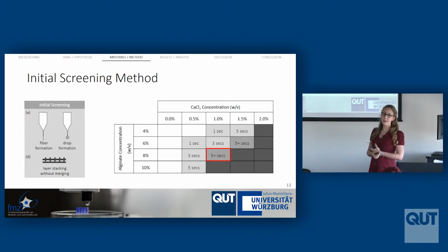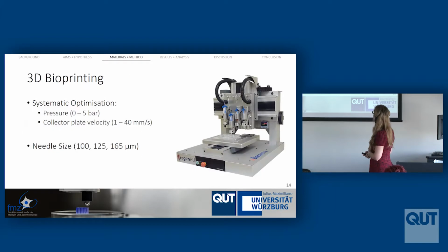So here's my beautiful bioprinter. This is my baby, and I was really fortunate to be able to use this over in Germany. It's a very expensive piece of equipment and really great to get some experience using it, which was awesome. So I could print with up to 5 bars of pressure. This means I could move between needing a lot of pressure to print some very, very firm materials, but also very small pressures for very liquid-like materials, and a range of different needle sizes as well, so I could get fatter and thinner fibers.